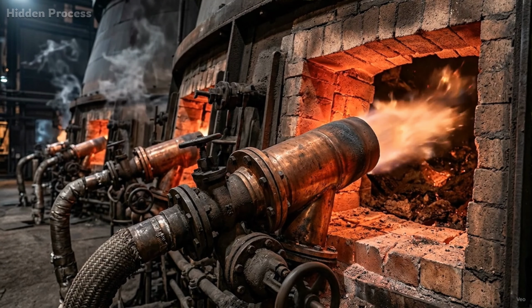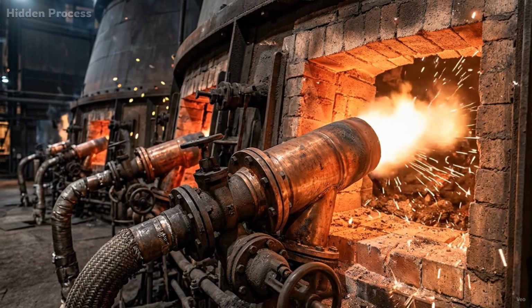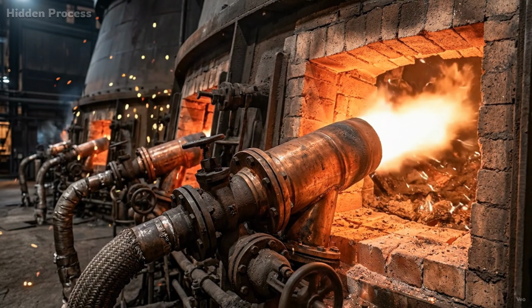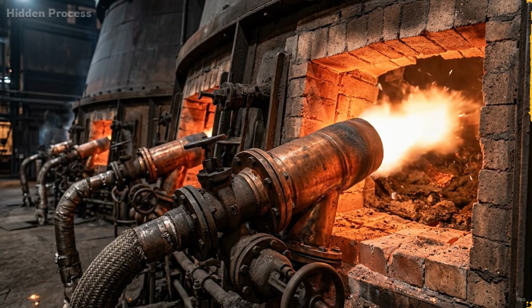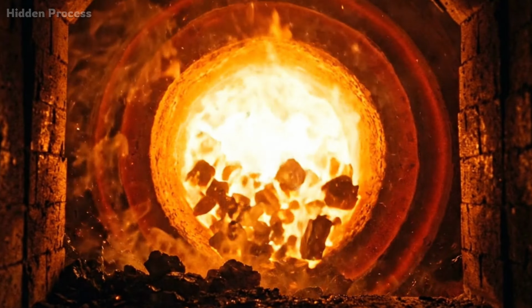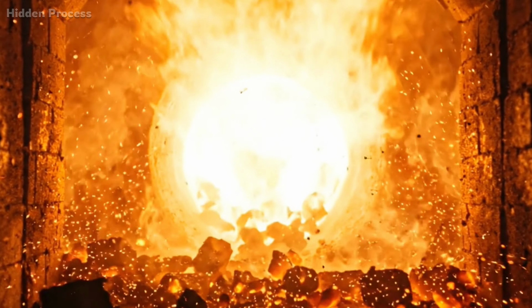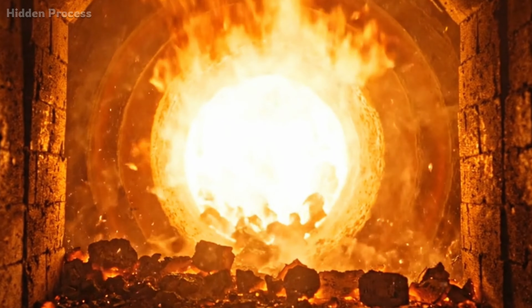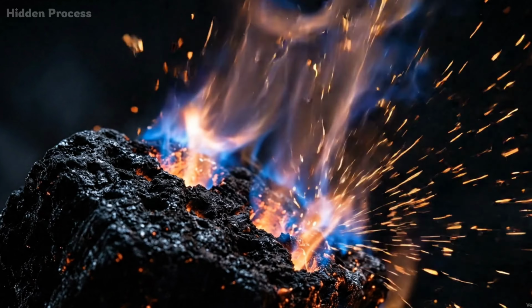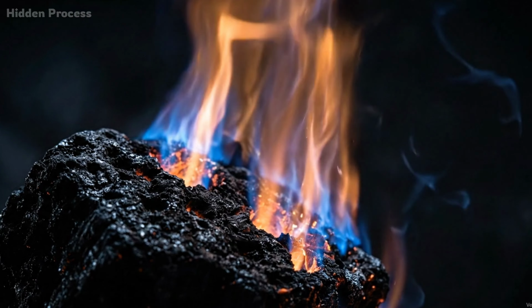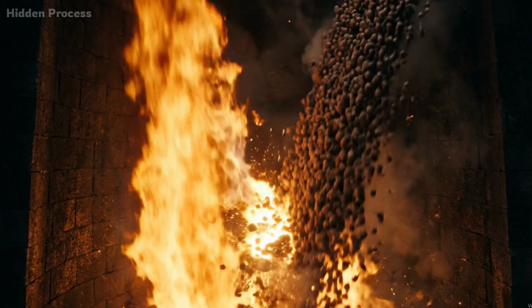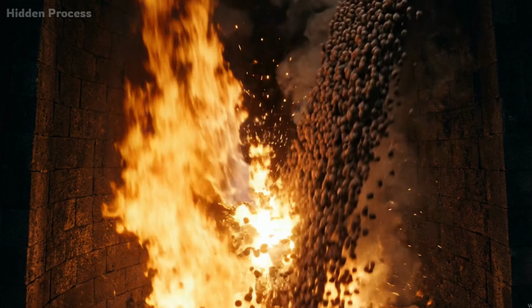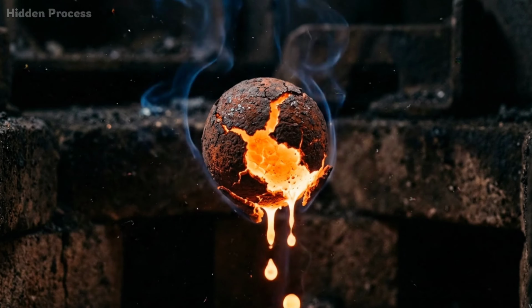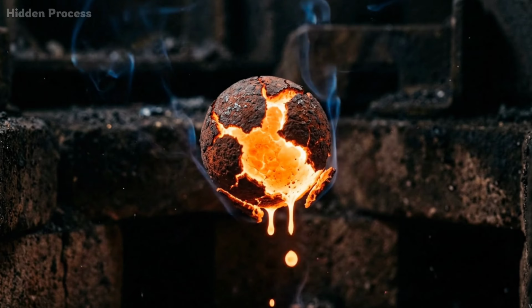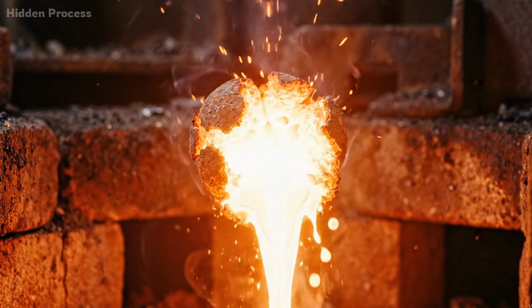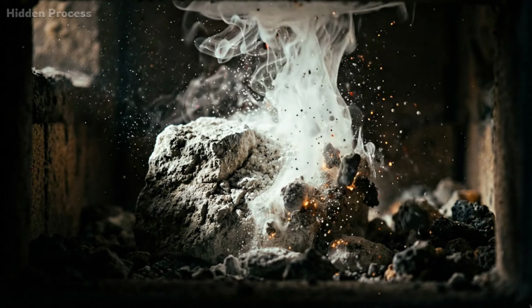At the base of the furnace, massive pipes called tuyeres blast preheated air, heated to over 2,000 degrees F, directly into the lower chamber. This superheated air reacts with the coke and creates temperatures near 3,000 degrees F at the core. At that temperature, the coke doesn't just burn, it combusts and produces carbon monoxide gas. And that gas rises through the furnace, reacting chemically with the iron ore as it descends. The oxygen is stripped away from the iron atoms, a process called reduction, and liquid iron begins to form. Meanwhile, the limestone is doing its job.